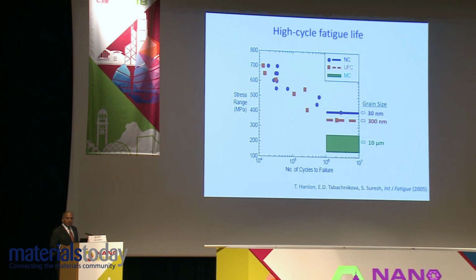So this is a classic S-N fatigue curve that you would see, and here is an effect of grain size on S-N fatigue life, as well as the number of cycles to failure and the fatigue endurance limit. If you have a conventional microcrystalline material, this is nickel, a pure nickel. If you have microcrystalline nickel of a grain size of 10 micrometers or so, you get a few hundred megapascal endurance limit, approximately 40 to 60% of the yield strength or the tensile strength of the material.